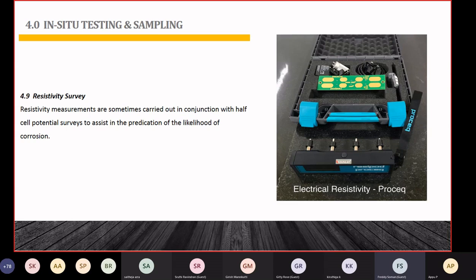because, as we know, these are all electronic equipment. In order to make our interpretation 100% accurate, we always try to do resistivity alongside the half cell survey locations as a reconfirmatory test. For example, if half cell potential shows that corrosion activity is certain in an area, and that is again underlined by the resistivity survey readings, then we can conclude that corrosion is 100% certain in that area. That way, as a reconfirmatory test, we do this resistivity survey also. Okay, sir. Next slide.